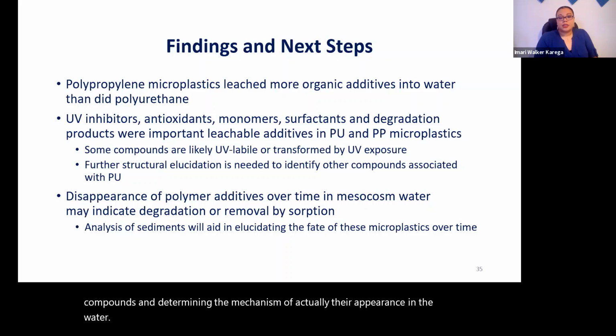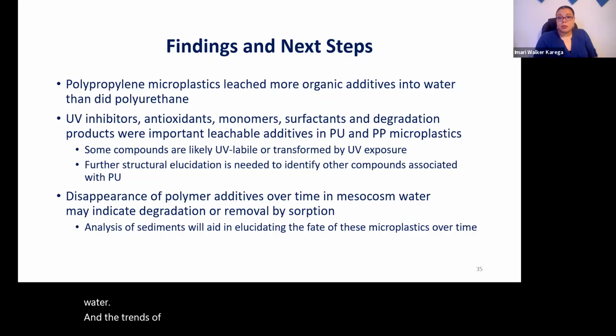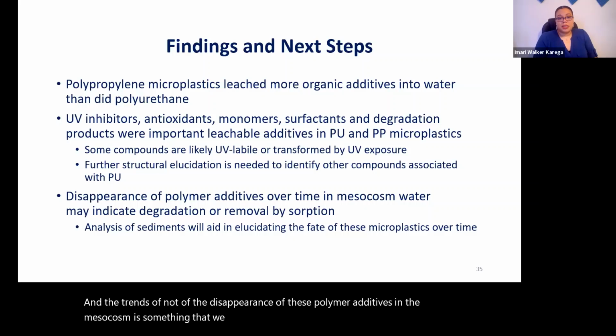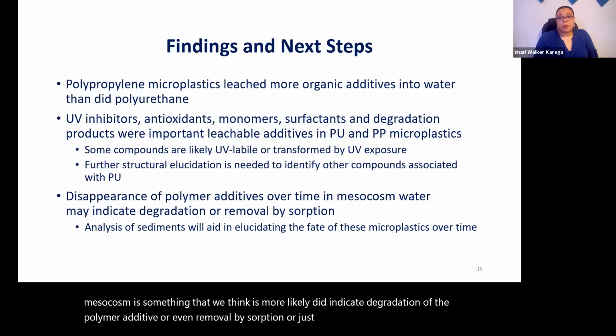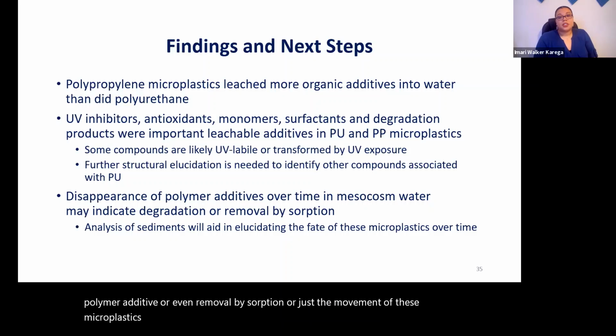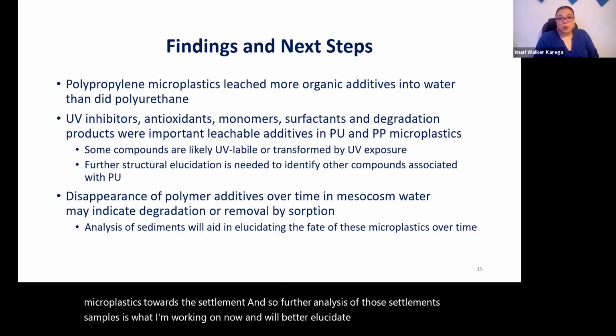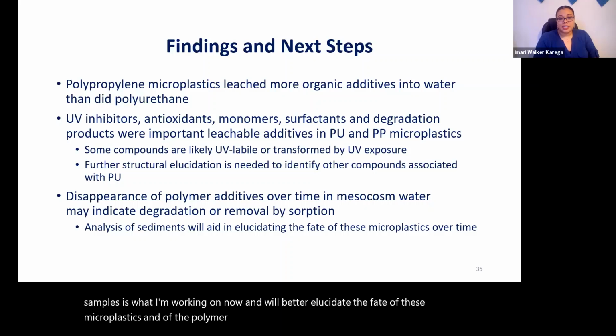The trends of disappearance of these polymer additives in the mesocosm likely indicate degradation of the polymer additive, or even removal by sorption, or just the movement of these microplastics toward the sediment. So further analysis of those sediment samples is what I'm working on now, which will better elucidate the fate of these microplastics and their associated polymer additives.